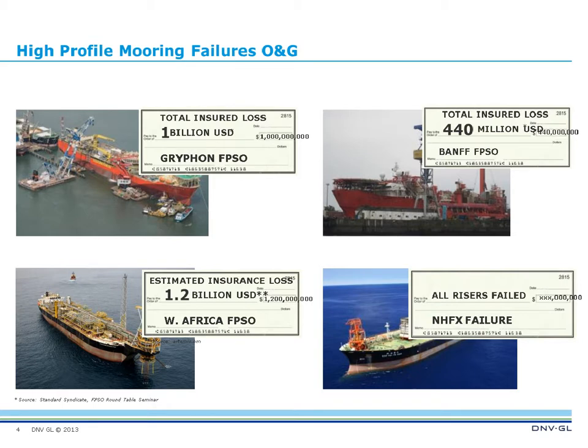The first two at the top are in the North Sea. For the Gryphon, the root cause analysis showed that the failure was due to combined thruster failure and flash butt weld of the chain, which led to poor quality. And for the Banff, it was undisclosed. The other two at the bottom are in Southeast Asia, where vessels are subjected to typhoon conditions, and West Africa, where corrosion can be a challenge. And I'll come back to this a bit later on.